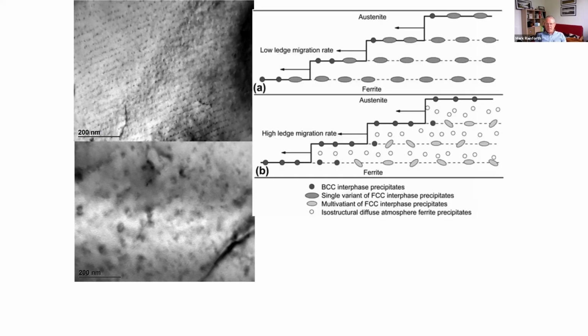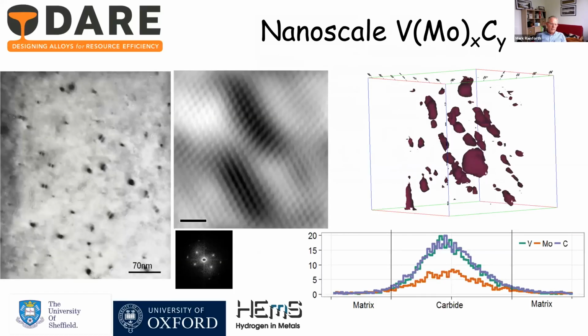But as I say, I'm taking a diagram here that's been around for a long time in terms of the mechanism of the austenite ferrite transformation producing precipitation in the process, which of course is still a matter of debate, but it's been known for a long time. But we have the ability these days to really see the atomic structure. So in the middle here, you can see the size of the precipitates, the slightly darker region in that high resolution image, but just a few atomic planes across.